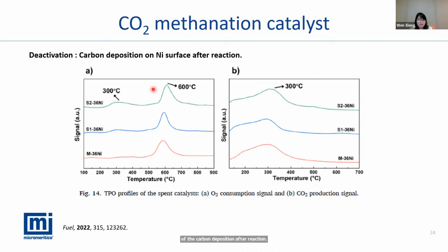I'm giving an example of the nickel. From the temperature program oxygen curve, we can see the oxygen consumption. So this is the oxygen consumption curve at 300 degrees C and 600 degrees C. The right figure is the CO2 production curve. If we look at 300 degrees C, there's information here. At 300 degrees C, we can see oxygen consumed and we can see CO2 produced.